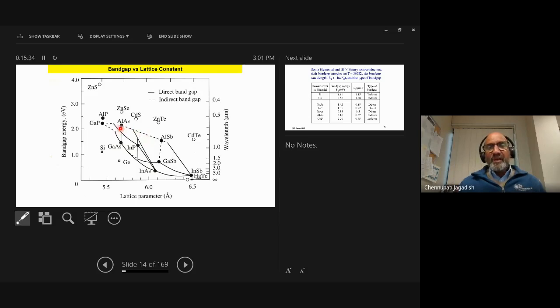And you can see that aluminum arsenide is not a direct band gap semiconductor. So not all compound semiconductors are direct band gap semiconductors. Some are and some are not. And you can also see that aluminum arsenide has a very close lattice constant to gallium arsenide. So that's why you can tune the band gap of the semiconductor here by mixing aluminum, gallium and arsenic. So basically you can tune the band gap, and that gives you a lot of flexibility. That means you can emit different colors of light, for example.